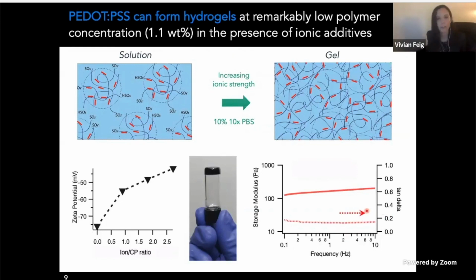So here on the right axis is tan delta, which is a ratio of how liquid-like to how solid-like the material is. And so we see that after aggregation, you're forming a material that has a tan delta way less than 1, indicating that you're sufficiently able to form this polymer network so that it's behaving like a solid within this frequency range. On the left axis is storage modulus, which is proportional to how stiff or elastic the material is. And here we can see that because the polymer concentration is so low, we're able to obtain values of around 100 Pascal, which is on the low end of that region we want for biointerfacing.